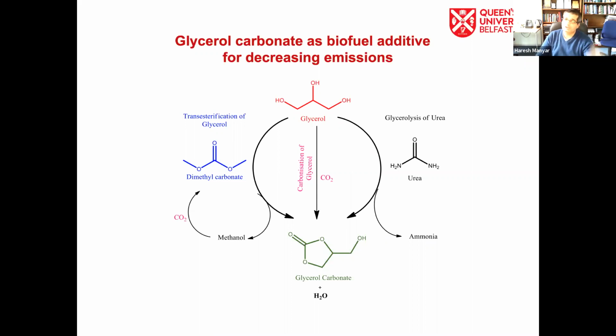Glycerol can be converted into glycerol carbonate by two different pathways. It can be converted by a direct route, using CO2 as the carbonating agent, or by an indirect route. The indirect route will require a transesterification agent like dimethyl carbonate or urea. The byproduct from the dimethyl carbonate will be methanol, which can be recycled to make more dimethyl carbonate, or the byproduct from the urea would be ammonia. But these can be recycled again. And if we look at these two pathways, we can make glycerol carbonate very efficiently.